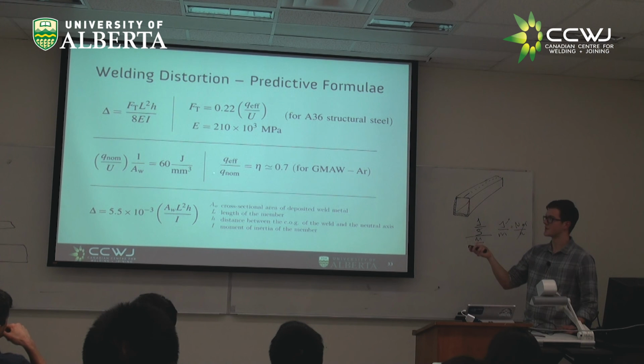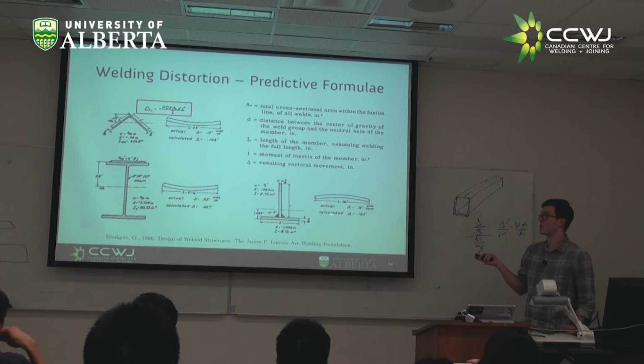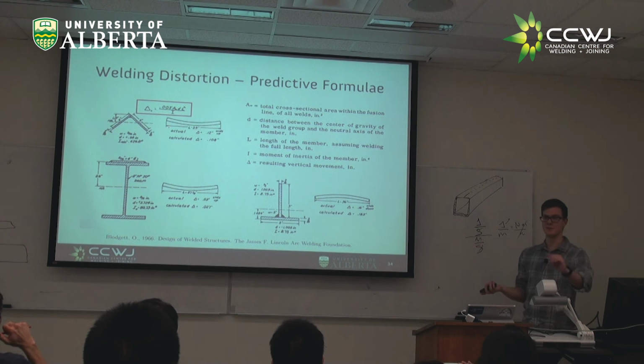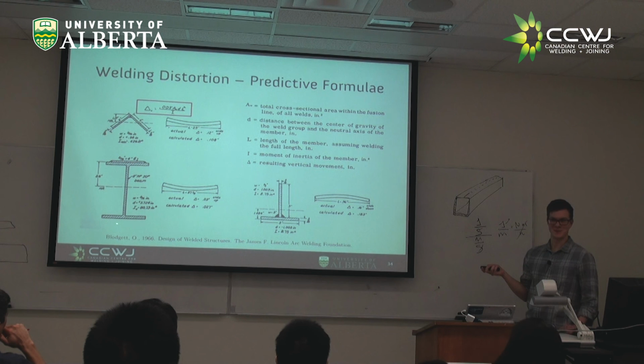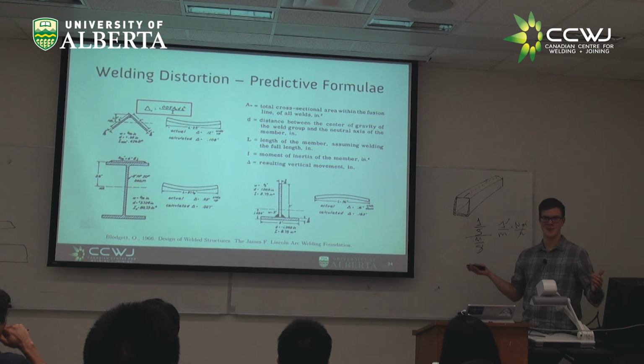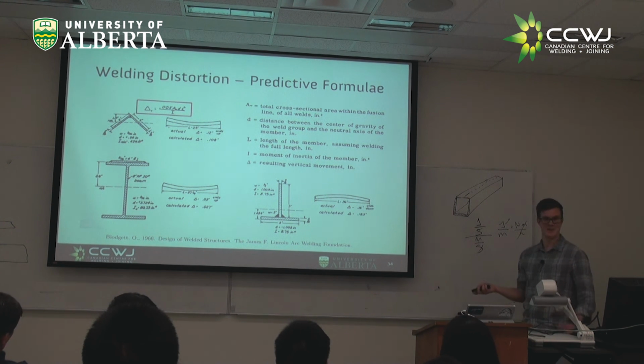Now, this is nominal, because that's how this expression was derived. This is effective. So we also have to consider the ratio of effective to nominal, which is our thermal efficiency, and we get about 0.7. That's for GMAW with argon. Now, were they using GMAW with argon? They don't say, but in that ballpark would not be unreasonable for any GMAW or stick process. I think GMAW with argon seems reasonable, because if you're manufacturing long beams, even in the 60s, you don't want to use stick welding. That's going to take you all day if you've got stick welders swapping electrodes. You imagine using a wire-fed process, probably going for high efficiency, so spray transfer, getting a lot of material down there, so you want to have some argon.